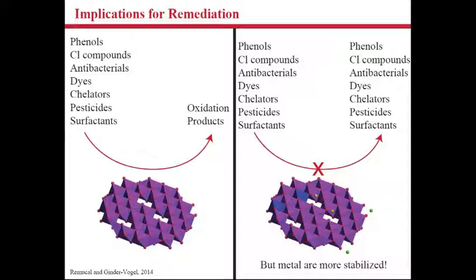Their study indicated that the oxidation from cobalt 2 to cobalt 3 happens at the edge, and the incorporation happens at the hole. So potentially, there could be an electron passed. It's potentially not the same atom, is sort of what I think is the implication, even though they never came out and said it. So potentially, you could have electron transferred from here to here, and then the drop-in, as opposed to the old model, which basically was that it all happened at the vacancy.